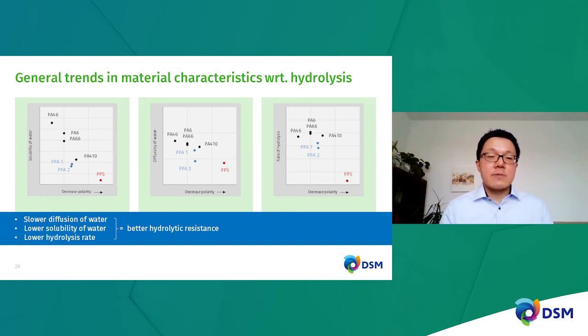So just looking at this picture, it's very clear that in order to have better resistance towards hydrolysis, of course, naturally, you want to use less polar polymer. So instead of using polyamide 4,6, you use polyamide 410 or PPS, because all these three parameters are usually pretty low. So if you look into the solubility of water, diffusivity of water, as well as the rate of hydrolysis, for PPS they are comparably low compared to 4,6. And if all these three parameters are low, you by definition also have better hydrolytic resistance.